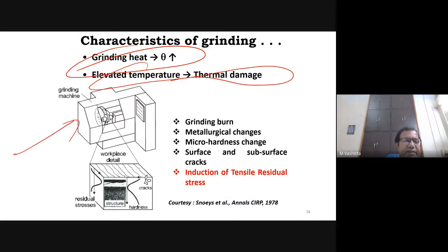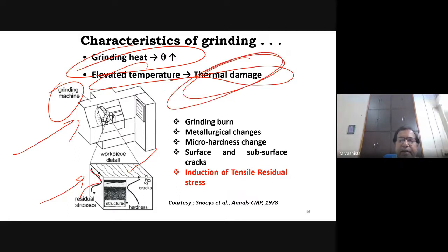Considering this is a grinding machine, and a rectangular workpiece, I can say that the surface texture will change. Because of the thermal damage, residual stress of tensile nature will be generated. Microstructure will be different. At the top surface, the microstructure will be retained martensite or retained austenite, and the bulk material has a different one.